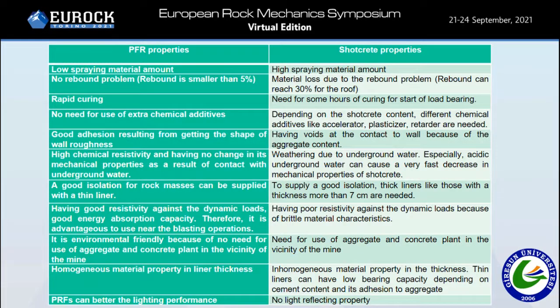In addition, its high deformation limits make PRF liners usable in rock masses with squeezing and clay swelling problems. Its good energy absorbing capacity and rapid polymerization are also advantageous for eliminating the fresh liner cracks induced due to the blasting operations. In addition to the body strength of the liner material, their adhesion performances have a great importance for the support reactions and the load bearing capacity. As obtained from the study, the PRF liner material has proper adhesion to rock values. Using no aggregates in the PRF liners is a significant advantage in terms of having a good adhesion performance.